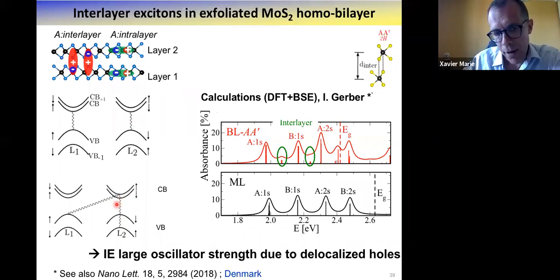At the beginning, you have the spin splitting of the conduction band, which is not so large. But then the key ingredient is to take into account that we measure excitons. We do not measure a transition between single particles. And it turns out that the binding energy from these calculations, which more or less fits the experimental results, the binding energy of the interlayer exciton is weaker than the binding energy of the intralayer exciton. So when you consider the energy position of the interlayer exciton, we should not take into account only the energy position of the bands in a single particle picture, but also the difference in binding energy.